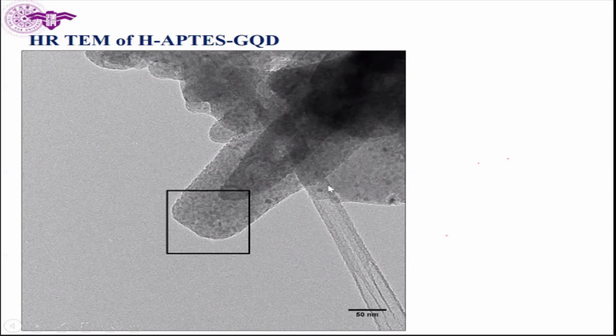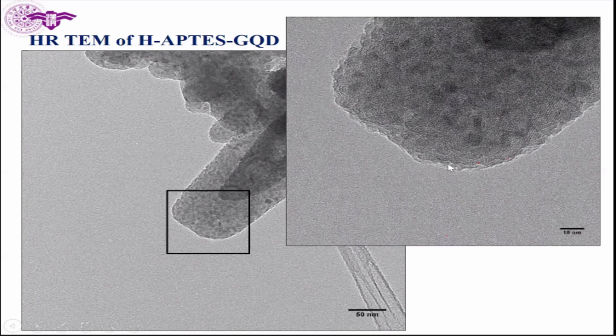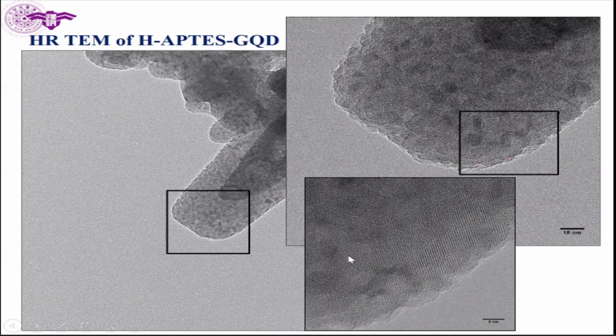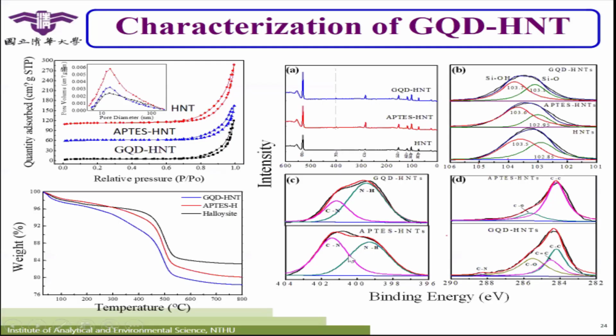And then when we put the APTES on the surface, the outside actually is the APTES. When we enlarge it, we can see some spots. This one is the graphene quantum dots here. Here we always will see their microstructures, including XPS, XRD, BET surface area, and the thermal property. I don't want to go into detail. If you are interested in that, you can read my paper. We published this one in 2018.